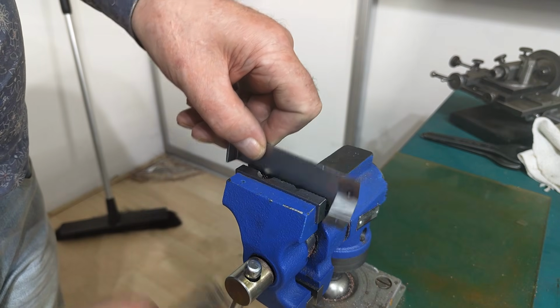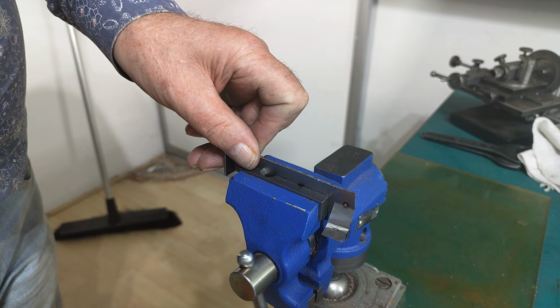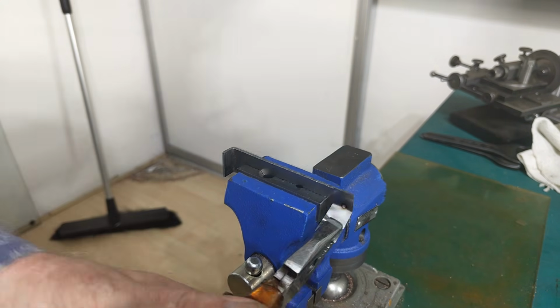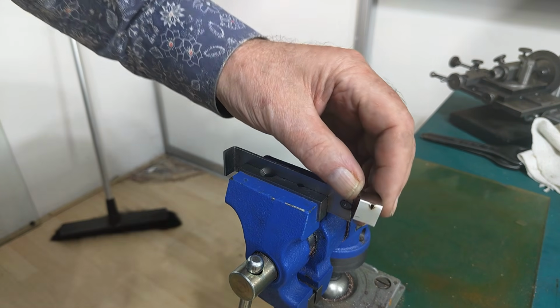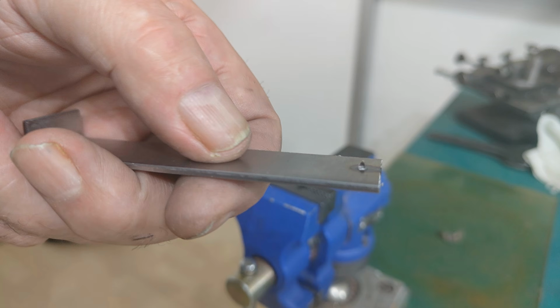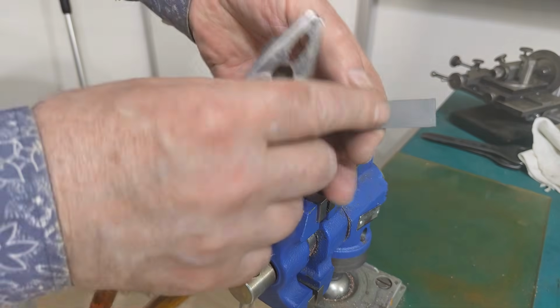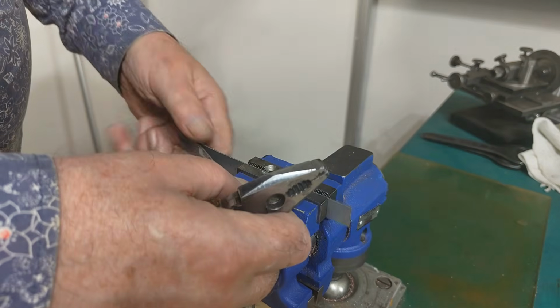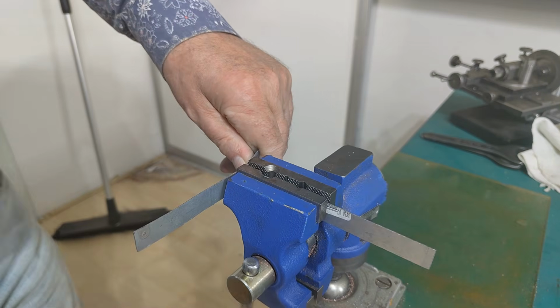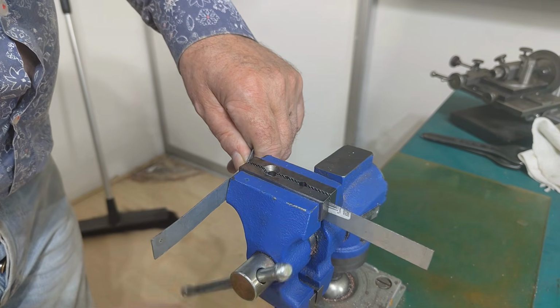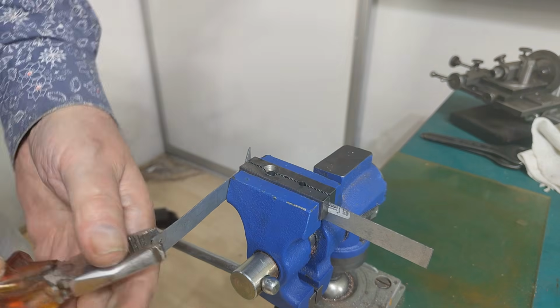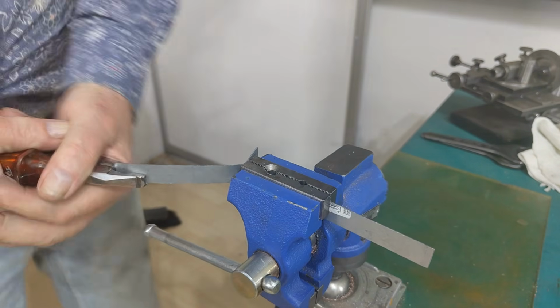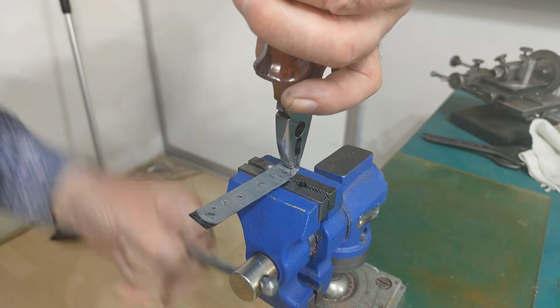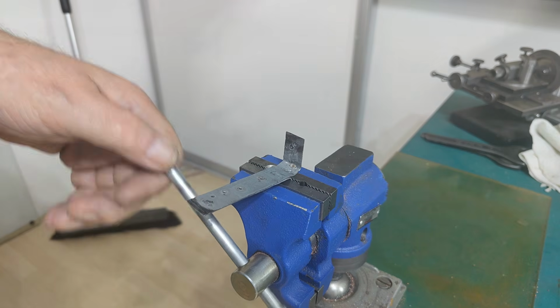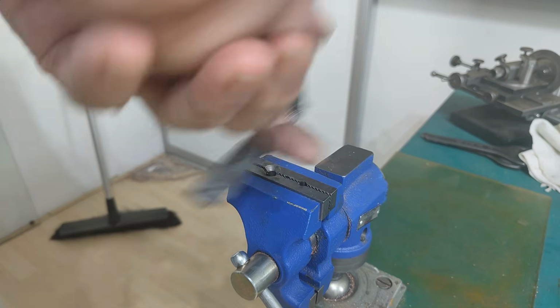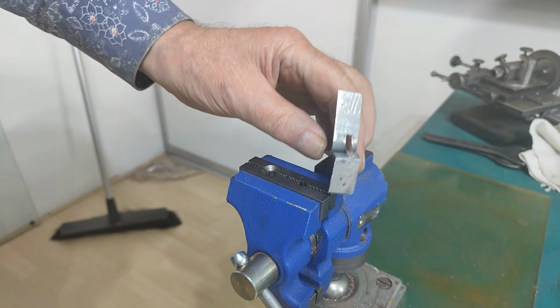This demonstrates that welding different types of steel together, in this case 2 mm mild steel and 0.5 mm stainless steel, is often perfectly feasible. Here too, the weld test shows a hole in the thinner material, showing that the weld itself is stronger than the sheet being tested. This machine produces strong, high-quality spot welds, and controlling the amount of energy delivered is remarkably straightforward.